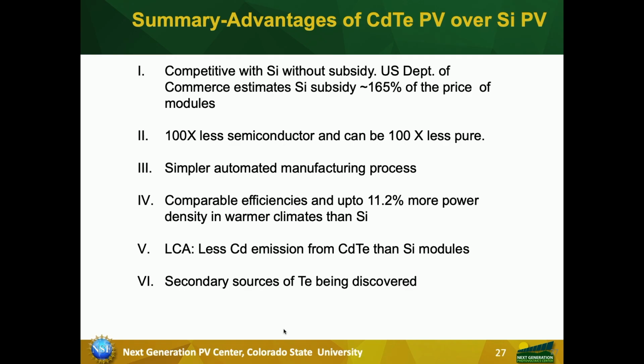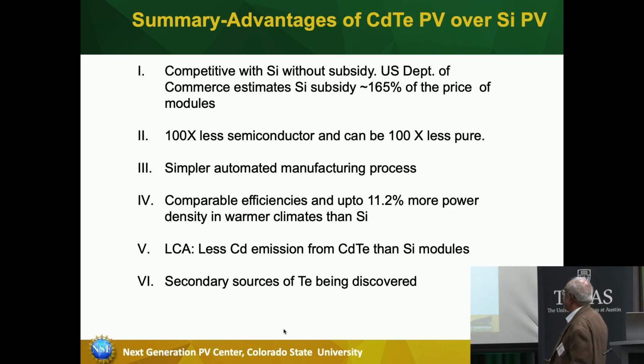So here is a summary of comparison between this. Competitive with silicon without subsidy. The US Department of Commerce estimates the silicon subsidy is about 165%. I don't know if that's true or not, but this is a number that our Department of Commerce came up with a few years ago. This is not the current number, which I don't have. It takes 100 times less semiconductor material that can be 100 times less pure. Because it's a direct band gap, it doesn't have to be seven nines pure. Silicon is an indirect band gap, so it has to be seven nines pure.